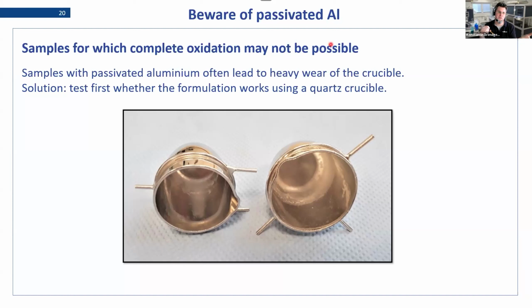Now, when this goes into fusion and you dissolve it in tetraborate, it becomes very reactive, and it has the effect on platinum that it causes a very high wear on your crucibles. They don't destroy a crucible immediately, but you can see something like this after just doing one fusion with these materials. So you want to be very careful with that. One solution is to dissolve it in acid and then dry it again. But also, if you're unsure about your sample, you can use a test crucible, for example quartz, to check if your sample has this effect before you actually use your standard laboratory platinumware and endanger it, so to say.